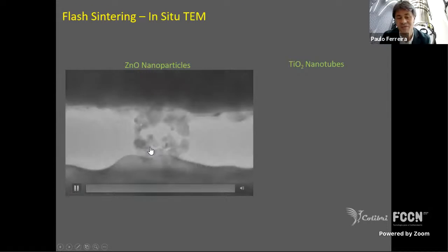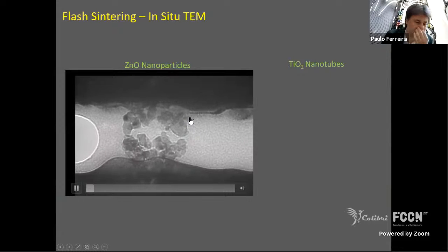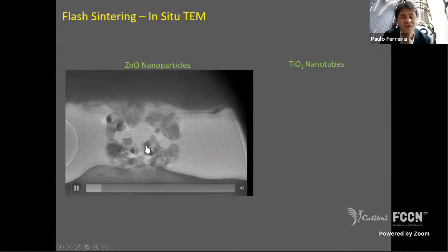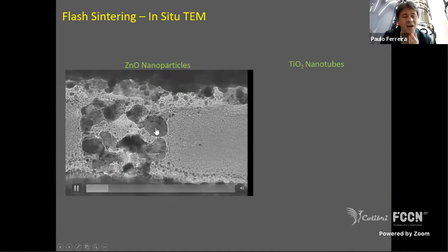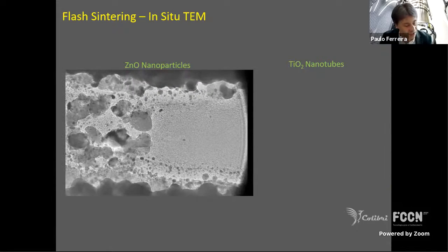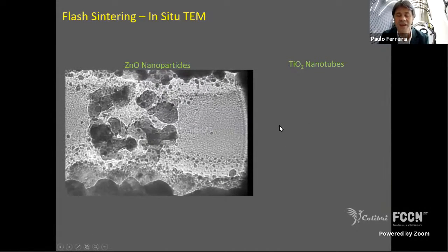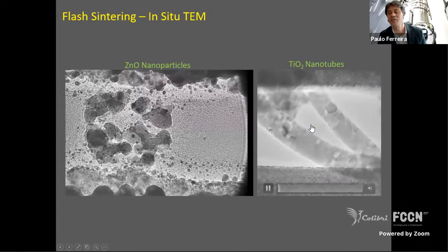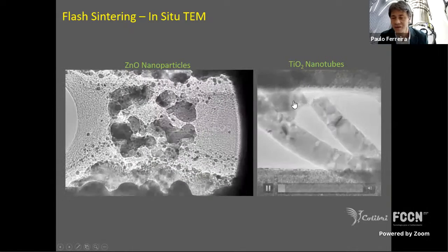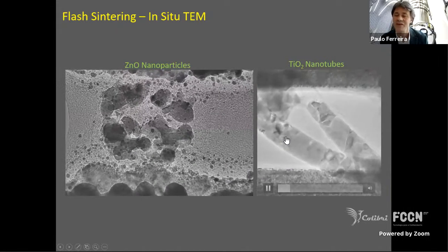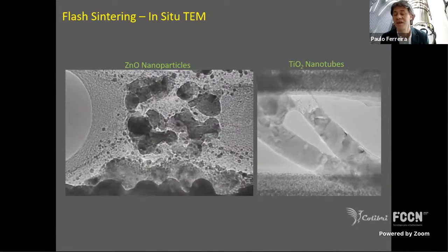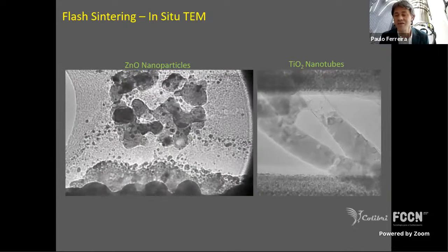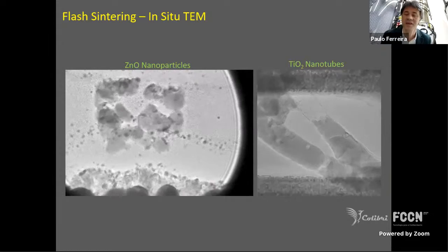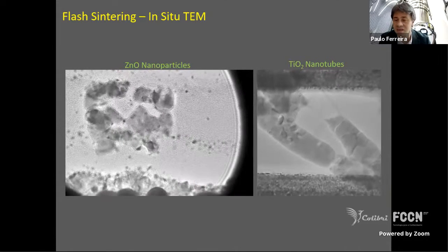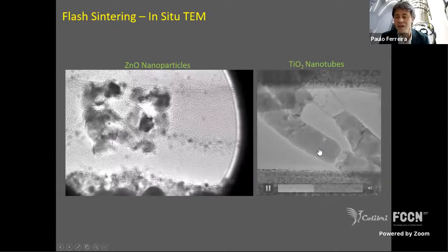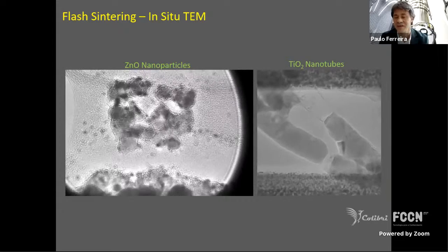So you can take these particles and sinter them with a field very quickly at low temperatures. Here are some things we have been doing where we are trying to understand this at the atomic level. This is with zinc oxide, trying to see how they sinter. This first experiment was extremely fast, and they emit light during the process. And here on the right is with TiO2 nanotubes. You can see that as you apply temperature and field, there's a polycrystalline structure here. But as you get this going, you get basically to a single crystal, and you even go to the melting state. The mechanisms by which the field does this are still not well understood, but this material that was polycrystalline is now becoming almost like a single crystal, because of this sintering process.